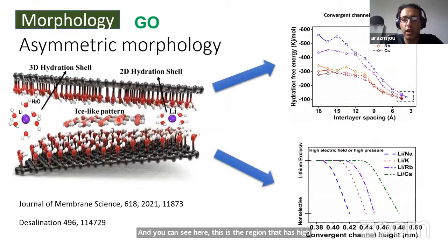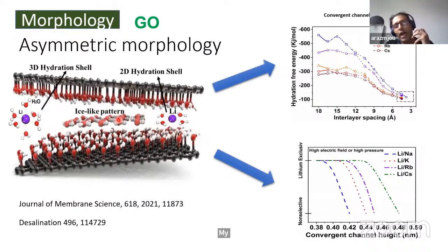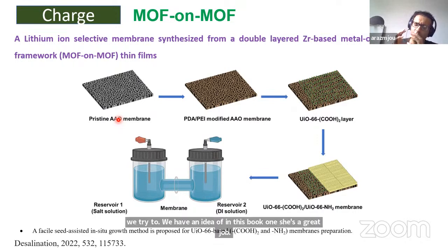My student, we tried different types of MOF on MOF. In this work, she did a great job. The idea was, when we make a lithium selective membrane, that membrane works very well for a specific brine, whereas if you just change the brine, your membrane may not work as well as it did with the previous brine.